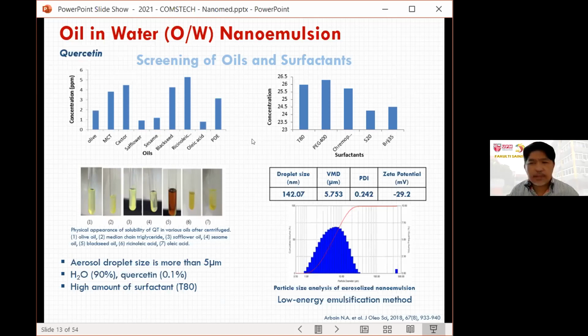Of course, for the surfactant, we need to find a good surfactant so that it will not increase the toxicity, even though we want to solubilize as much drug as we can, but there is an issue with toxicity. So when we started from scratch, there was another thing that we needed to consider, the particle size. We were then able to get below 200 nanometer, particularly between 100 to 150 nanometer. But another challenge is to get the VMD, volume mean diameter, which is actually the particle size. I will explain this shortly.